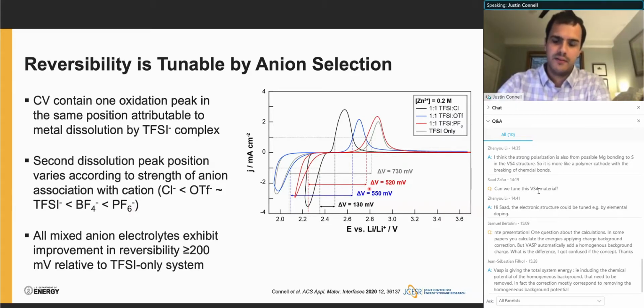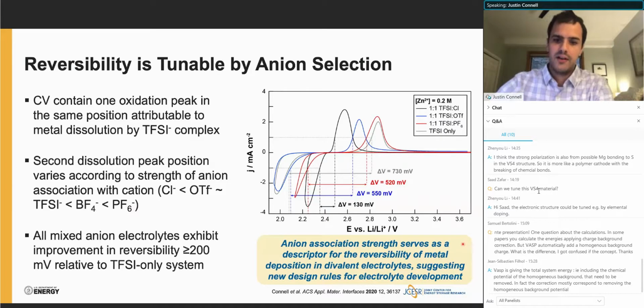Again, in keeping with the predictions of DFT, we see improvements in reversibility of greater than 200 millivolts for all the mixed anion electrolytes we've studied. And so what this tells us is that anion association strength can really serve as a descriptor for reversibility of metal deposition. And more importantly, it suggests a new set of design rules for electrolyte development.